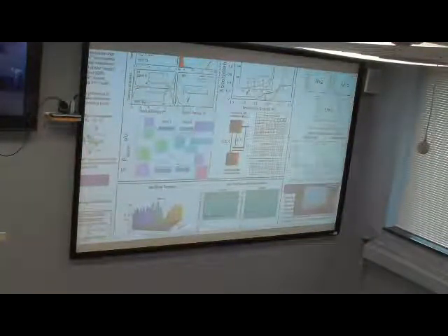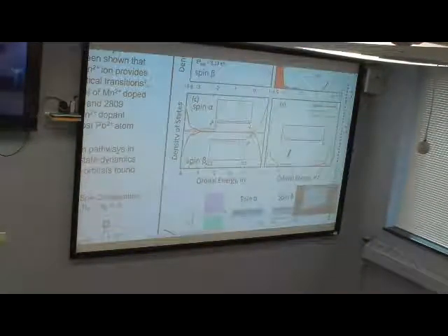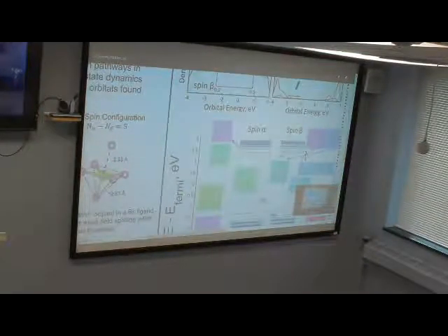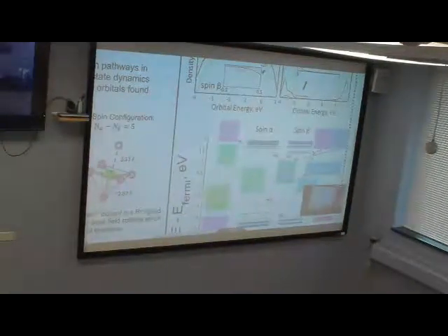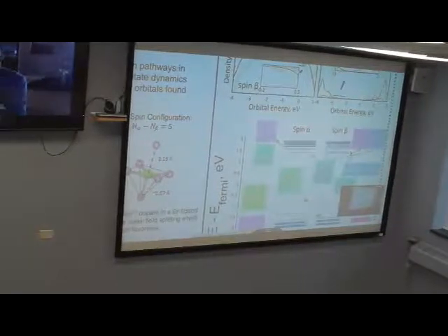It's about 40% metal ion, or manganese orbitals, about 40% bromine p. And then the other 10% is either ligand or s orbital, or Pb s. I guess it's higher, well, just looking at the image, you can tell. That's for the topmost state. This one, it's more like, I guess still 40% of the bromides around it, but it's less of the d metal.